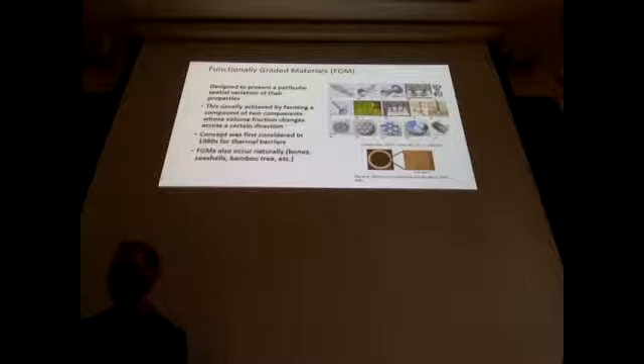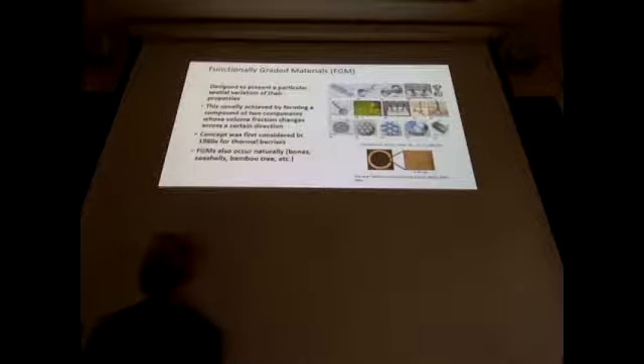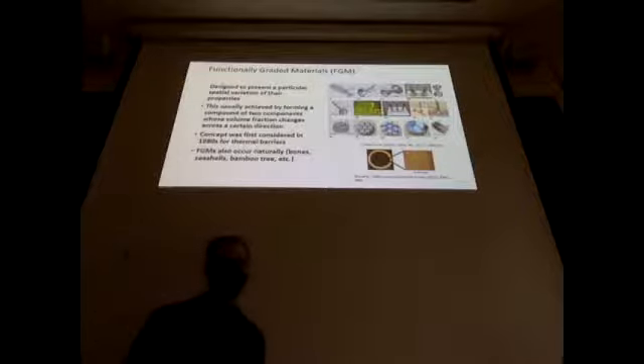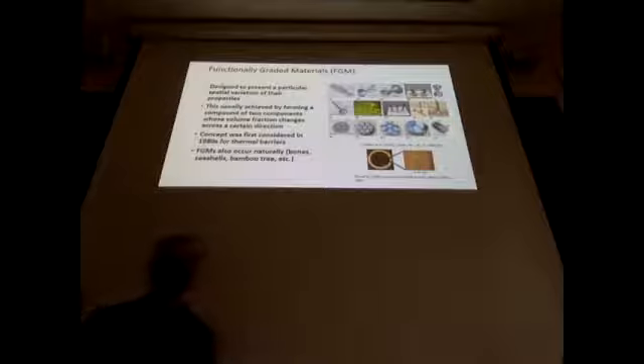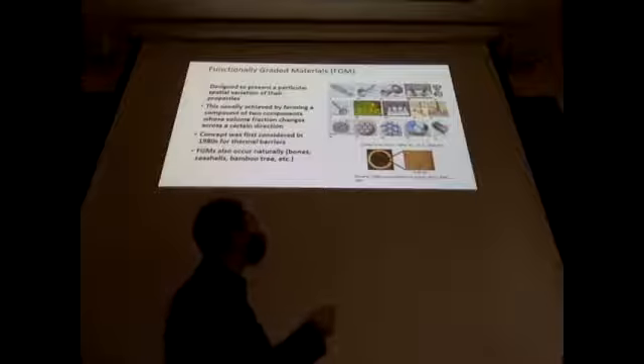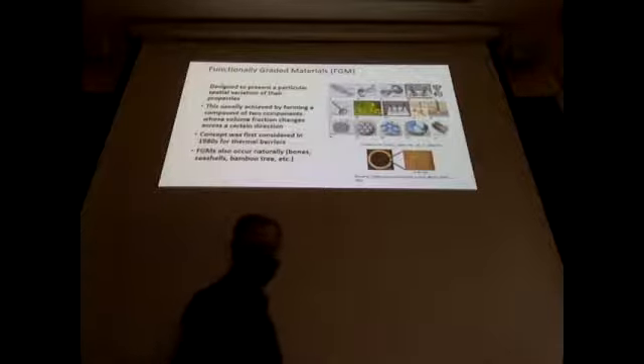It's usually, as I mentioned, done by adding two components together where you're trying to harness the benefits of both in your system. And the concept was first considered back in the 1980s. First it was done with thin film applications, but now they're doing more of what they consider bulk applications, which is what additive is doing. FGMs also occur naturally. You see it in bones, you see it in structures like bamboo, and you can see in the structure on the left. The idea is that in bamboo, the pores change depending on how close it is to that edge. And that's basically what a functionally graded material is, changing spatially.